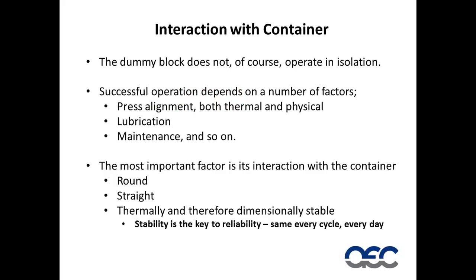Unfortunately, it doesn't operate in isolation. For successful operation, we need a press that's aligned, both thermally and physically. We need proper lubrication between the dummy block and the billet, also internally within the dummy block. But the most important thing that we require is a round and straight container. It needs to be thermally and therefore dimensionally stable. And stable is a word that you hear me say quite a bit, and the only way that we can have reliability is for the temperature and size to be stable every cycle and every day.